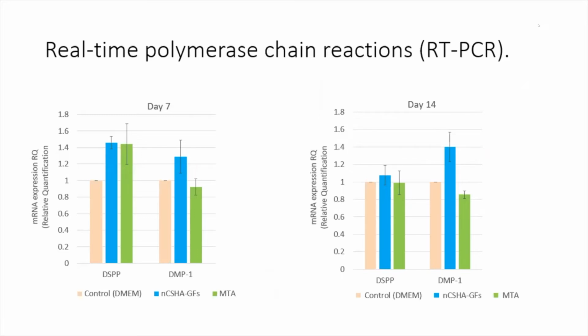And we also investigated some specific markers for dentin tissue regeneration. The result of RT-PCR analysis showed DMP1 mRNA expression had a significant difference between the extract liquid of our scaffold and MTA after 14 days. The NCSHA growth factor group showed a higher effect on mRNA expression of human dental pulp stem cells.